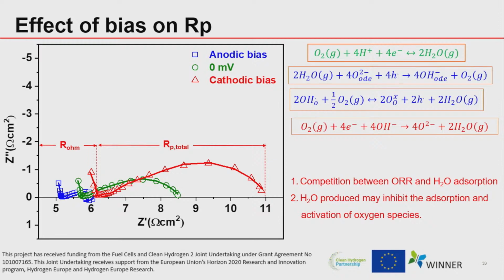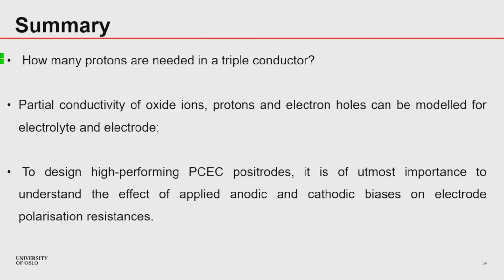But that might not be true, because we are producing water here, and there might be a competition between the oxygen reaction and the water adsorption. Also, the water produced may inhibit the adsorption sites. So if there is a competition for the active sites, the resistance has increased. If we improve the microstructure and give more active sites, this should not be the case. Depending on the material type, this RP increase or decrease may change. This was just a basic example to show what we can do with the biases.